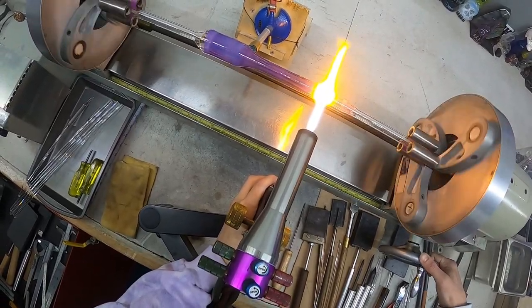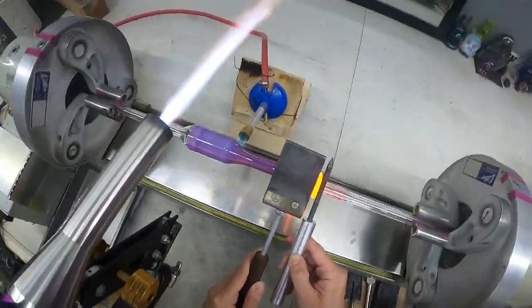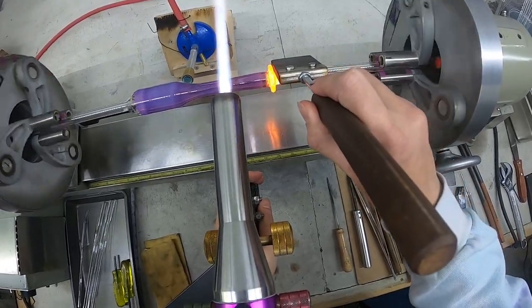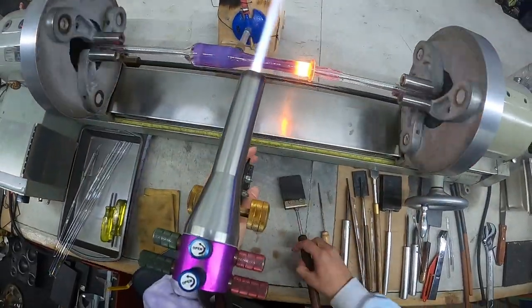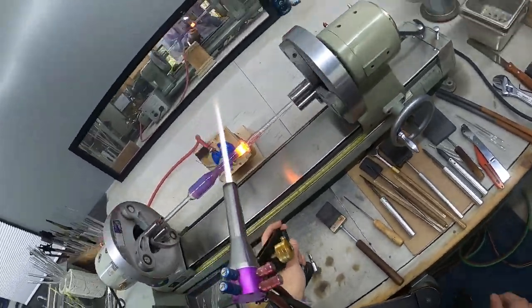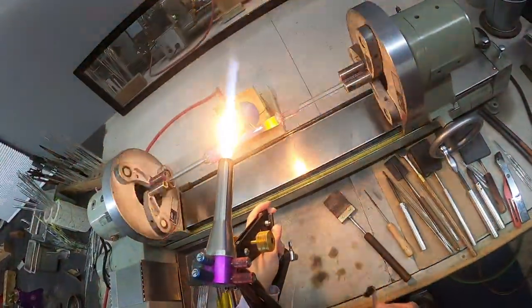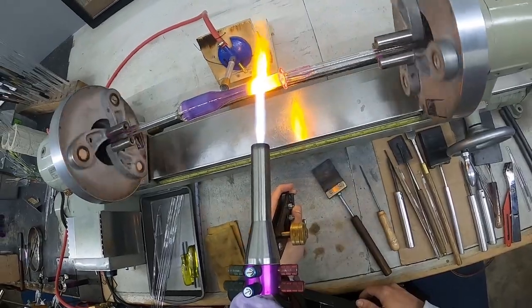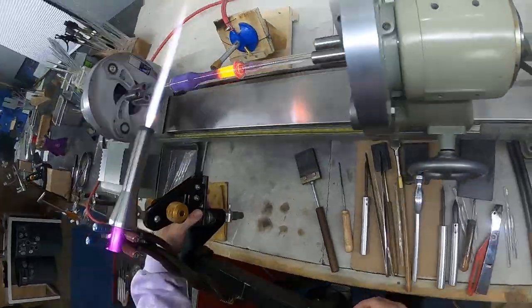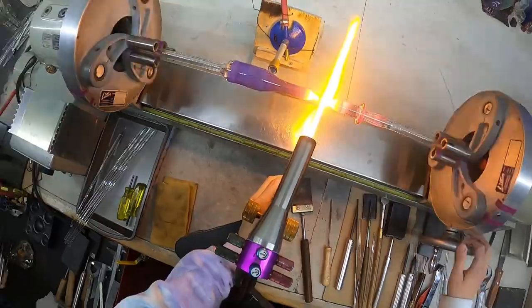Then basically doing a little marver right here. I use a paddle and a reamer to finalize my shape — it allows me to not trap air. I get it to right before it's about to trap air and then do that shape. You can actually see me moving the reamer down a little bit — that's how I collapse it down on itself without trapping any air. Very important, because if you see that air ring on a marver, it's just nasty.